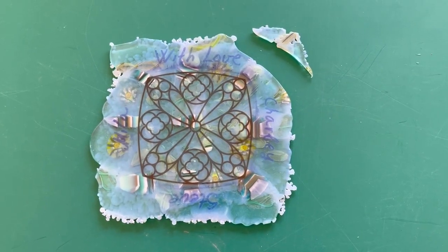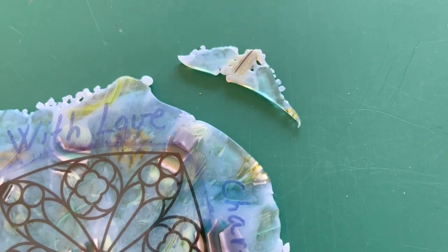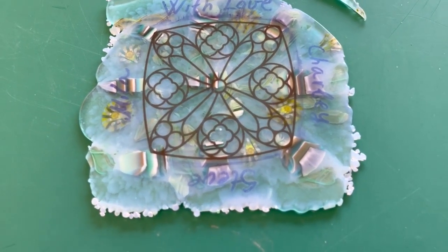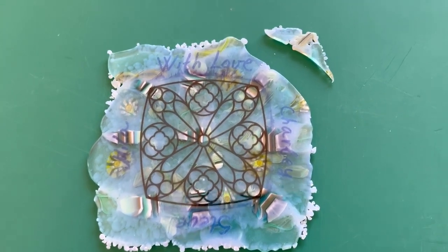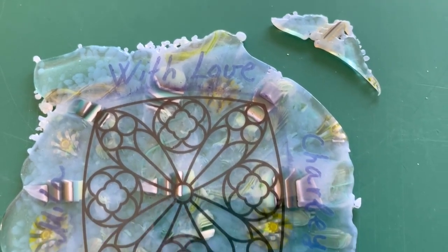So guttingly, we've opened the kiln and a piece has broken off. This is a fracture that happened on the way up because the edge is smooth. So it then did a tack fuse. I did a slow ramp, but I don't think this piece of glass was very well annealed when it was originally pressed. So that's probably why. We're gonna trim it off and hopefully make it into something even with this issue.